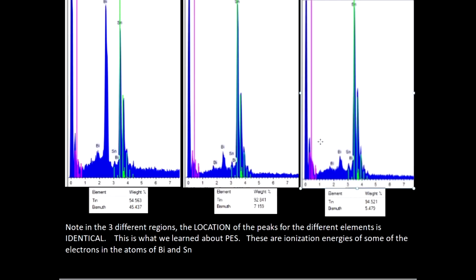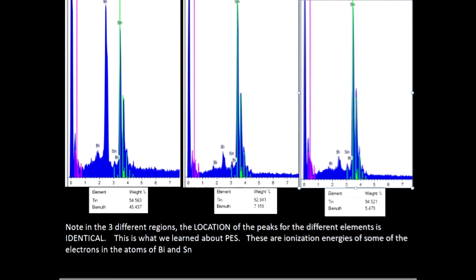you can see the location of the peaks match, right? Those are characteristic of any particular element. The composition, which determines the height of the peaks, the percent composition, I should say, is different, but it's neat how it just exactly overlaps. So it is characteristic. It's a fingerprint spectrum. And that's how we can use that kind of spectroscopy to identify what those components were.